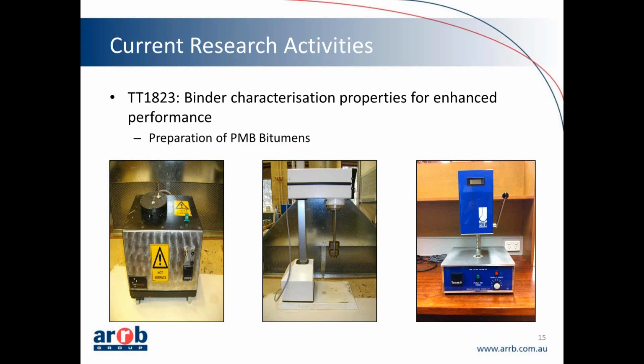And the challenge when we're making bitumens is how do we know when the polymer has been completely broken down into that bitumen. If we were to do testing with conventional tests, we could potentially be waiting up to an hour before we know whether or not that polymer is completely broken down. So what we've got there on the right-hand side is a cone and plate viscometer, and this is out of the UK. Basically it enables us to ascertain the viscosity of the bitumen within a couple of seconds. And when we reach a point where the viscosity plateaus, then we know that we've got the blending down. So we stop the blending process and then do the bitumen testing from there.